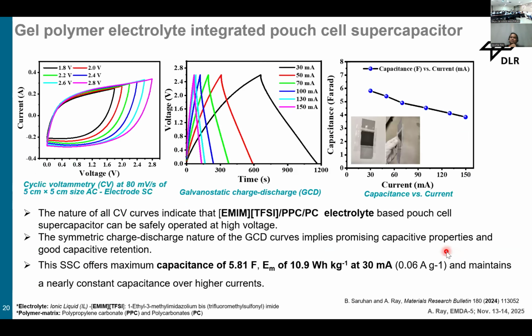So there is some of our recent work that was also published last year. You can check this paper and you will get more details about the work. From this cyclic voltammetric curve, you can see that for this research work we measured up to 2.8 volt, and all the CV curves give the same performance. Also the GCD curve gives high total capacitance, about 5 farad. And what is the electrode material? We used commercial activated carbon based electrode material, and we prepared in our laboratory a thin pouch cell of 5 by 5 centimeter size, and it gives almost 5.8 farad and an energy density of 10.9 watt hour per kilogram.